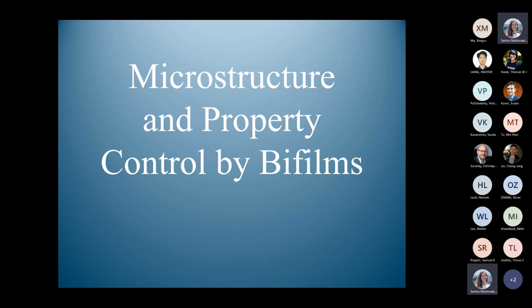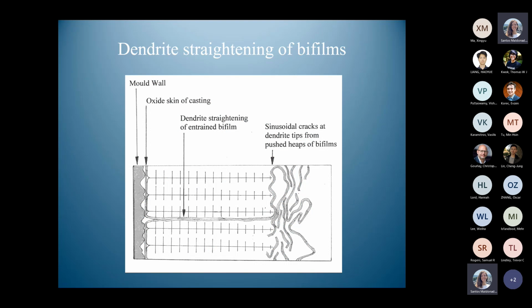So if we look at the properties and the microstructures, this is one of the ways in which, when we first pour, the bifilms are scrambled into the liquid in a compact way, but then the grains start to grow. Now, the dendrites can't grow through the bifilm because of the air layer. So they reach the first film. There's the layer of air before it gets to the next film. Clearly, the dendrites can't grow through the air. So all they can do at that point is push.